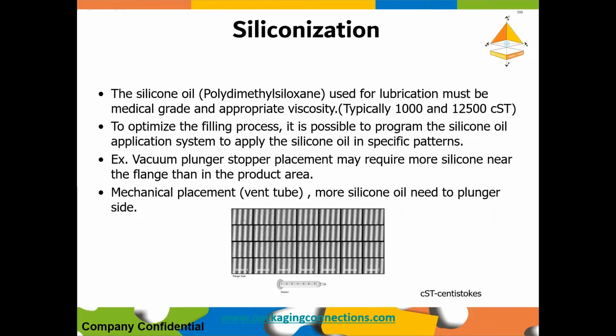Siliconization, the silicone oil, polydimethylsiloxane. It should be medical grade and of the right viscosity. So the application of this depends on the final filling. For example, vacuum plunger stopper placement may require more silicone near the flange than in the product area. Mechanical placement needs more silicone on the plunger side. So it's important.